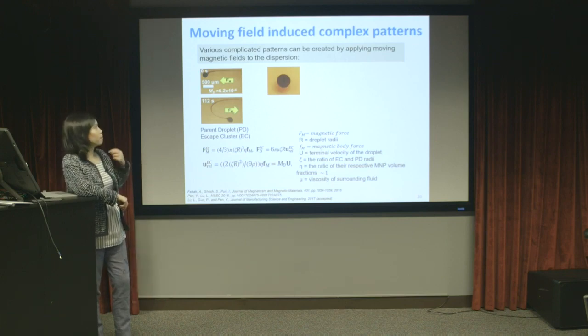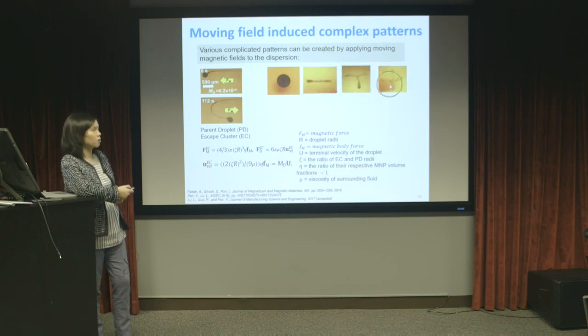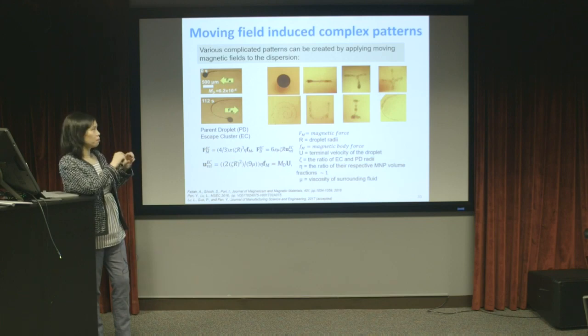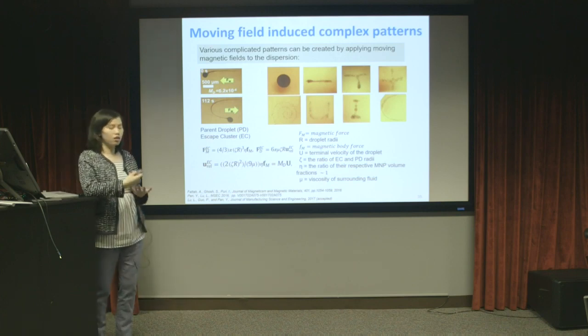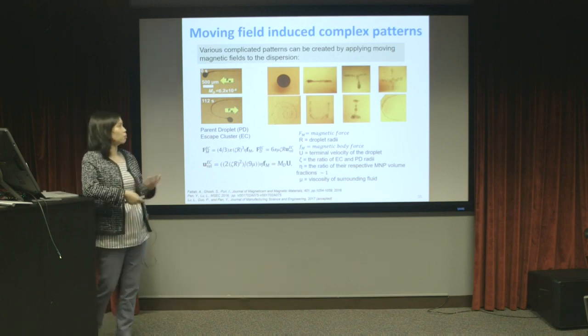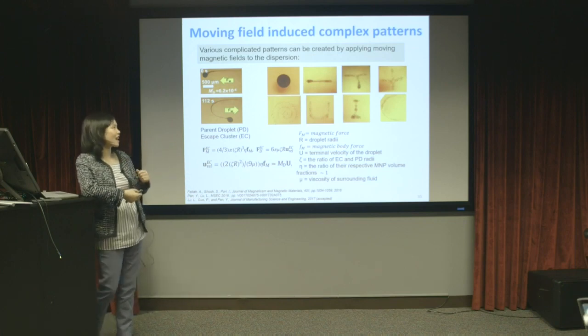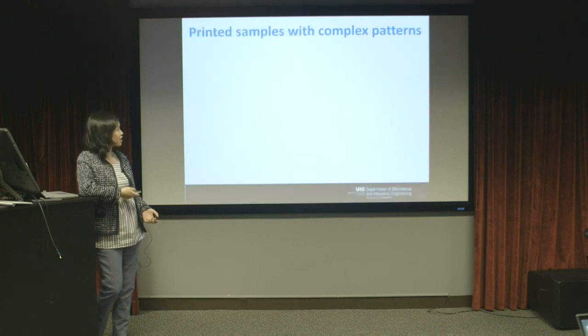So by using a moving magnetic field, we can attract this magnetic droplet and draw a pattern in the liquid resin. Starting from the droplet, we can form much more complicated particle distribution patterns, such as the line here and the T-letter here or the cross here, and some other complicated patterns. And we can also analyze the magnetic particle pattern size and the particle moving velocity in the liquid resin by considering the dragging force in the particle flow process, and also the magnetic force.